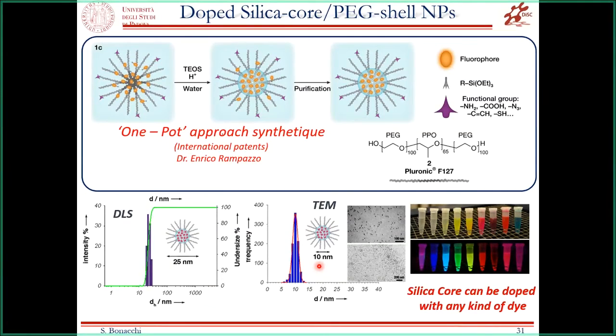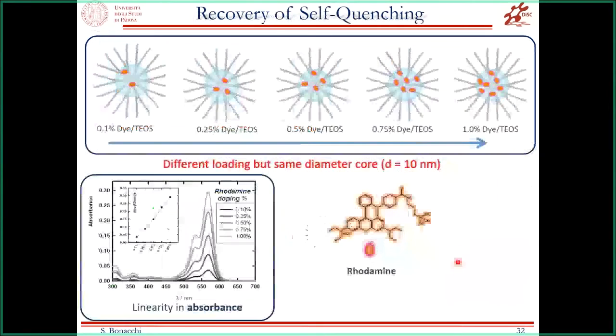So we are going, let's say, from atomically precise nanoclusters of around 2 nanometers to one order of magnitude higher: nanostructures that are not atomically precise anymore, but allow us to at least increase, as I showed you briefly, the quantum yield and the total brightness of this system. And in particular, with this novel approach, we were able to obtain different kinds of dye-doped silica nanoparticles, different colors with the same nanoparticle structure but different dyes, a sort of rainbow of colors of doped silica core PEG shell nanoparticles.